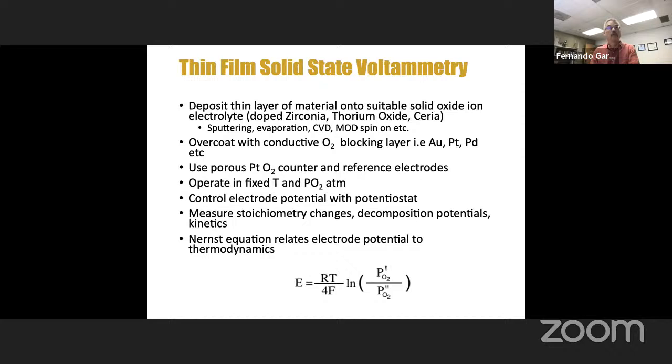We operate the counter and reference electrodes at fixed oxygen partial pressures as a reference. So we reference to oxygen, the chemical potential of oxygen in air at the relevant temperature. We control the electrode potential with a potentiostat, and we can measure the stoichiometry changes, decomposition potentials, and kinetics. And we can relate these to the Ellingham diagrams, which we saw before, by the familiar Nernst relationship that the cell voltage, if your cell is designed properly, is related to the ratio of the effective oxygen partial pressure